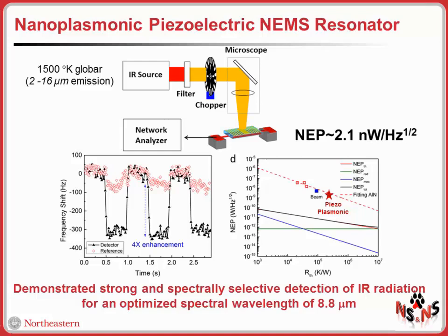And we measured, of course, the noise performance and the thermal sensitivities. For this prototype of spectrally selective IR detector, we measured a noise equivalent power of about 2.1 nanowatts per square root of hertz, which is really among the best, to our knowledge at least, compared to other spectrally selective thermal detectors. What I'm showing you in this plot is that although we are quite happy with this performance, there is still a relatively large gap between the measured noise resolution of the device and the theoretical limit that is set by thermomechanical noise and thermal fluctuation noise. So definitely there is still margin to improve the performance of this device, and that involves really understanding what are the main noise sources that are adding noise to the system in addition to the fundamental thermomechanical noise.